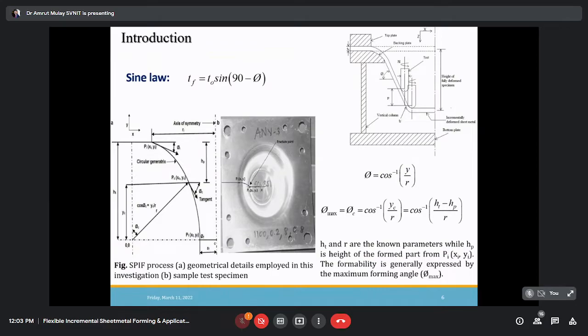And people have tried different geometries, because the geometry of the part also has an effect on the formability. That needs to be investigated. Now you can see that this particular geometry is a varying wall angle conical frustum. What does it mean? When you take a tangent at any portion of this line, this is the geometry, according to which this product is being formed. It means that when you take a tangent anywhere, the tangent angle phi will not be the same. Here the phi values range from 30 degrees to 90 degrees.